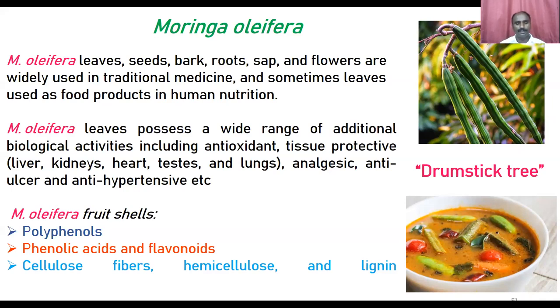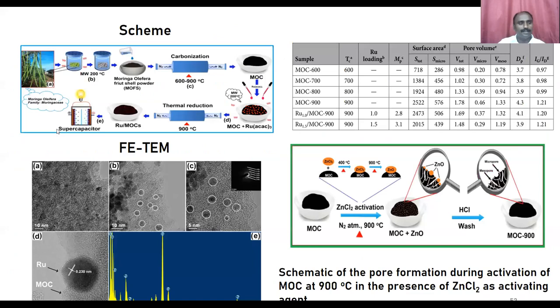So these chemicals, these substances, this moiety is important for the preparation of activated carbon. So I chose Moringa oleifera as a key material for the preparation of activated carbon. I collected the Moringa oleifera, chopped it into small pieces, and heated it with microwave radiation at 200 degrees centigrade.